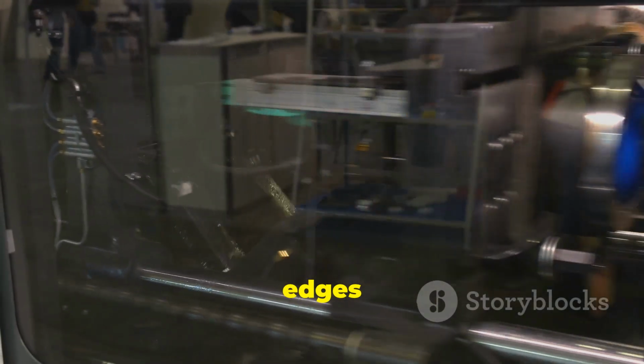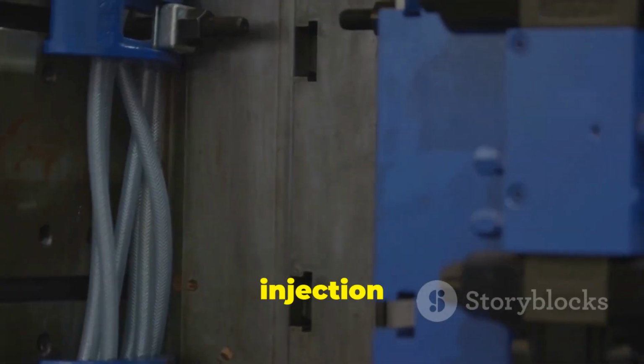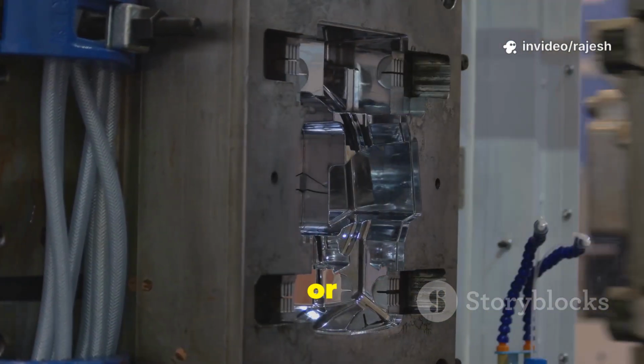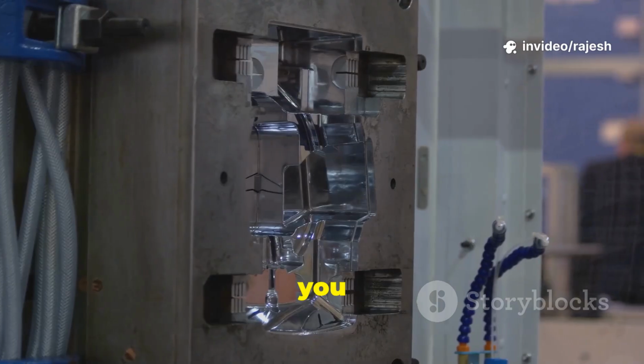Next, you'll notice a thin, almost paper-like layer of plastic sticking out along the edges or seams. Not good. Flash is usually caused by too much injection pressure, worn molds, or not enough clamping force. If you see flash, the mold probably isn't sealing tightly or you're pushing the material too hard.